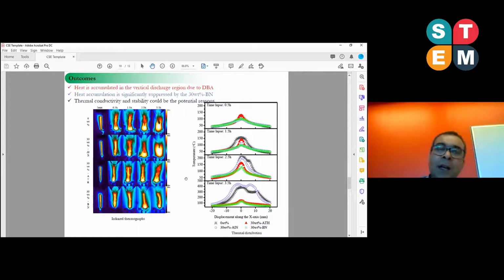Here is the infrared thermography. We measure the temperature distribution on the surface of the insulation. Here we can see the main heat is accumulated in the middle of each sample, because the liquid is flowing in the middle of the sample. So major dry band arcing is seen in the middle of the sample, and the main heat is accumulated there.